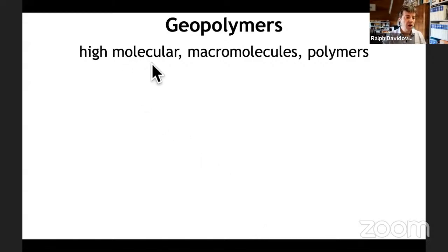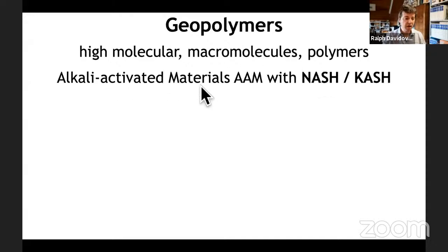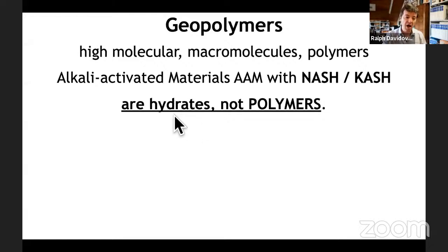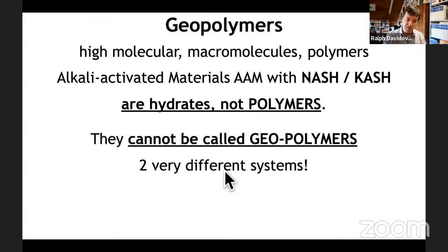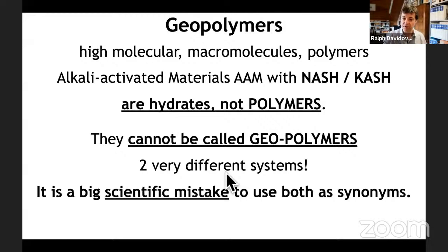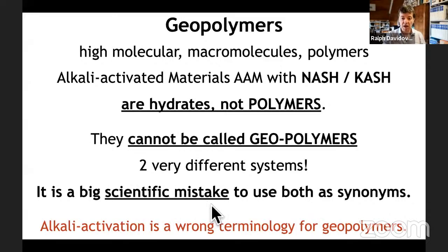Geopolymers are high molecular macromolecules, polymers. Alkali activated materials, AAM, with N-A-S-H and K-A-S-H, are hydrates, not polymers. They cannot be called geopolymers. These are two different systems. It is a big scientific mistake to use both as synonyms. Alkali activation is a wrong terminology for geopolymers.